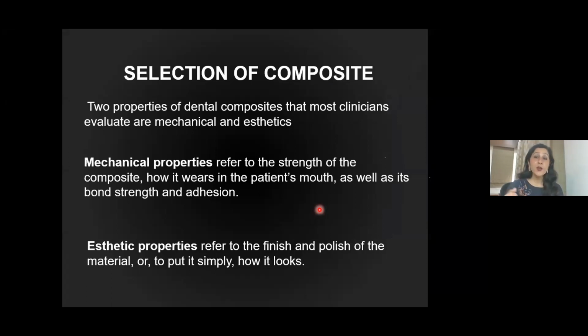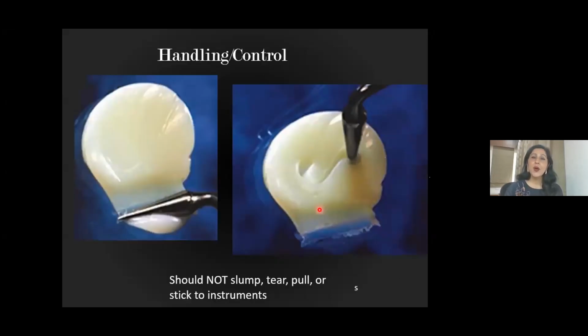When you use it for posterior teeth, it should give you strength, good bond strength, and adhesion as well. And when you use it for aesthetic properties, then it should give you a good finish and polish with good shade matching. So handling of composites should be done in such a way that they should not slump, tear, pull, or stick to instruments. Because many a times it is so frustrating that your composite will not stick to the tooth, but it will stick everywhere else. But where it has to stick, it will not stick there. Why does this happen? This happens because your instruments